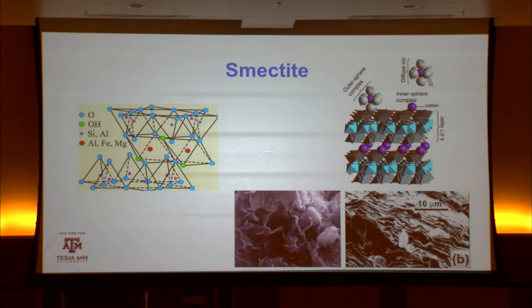So if you look over here to the right-hand side and you see the silica, oxygen, and silica layers, and then you see another basic stack of those layers, or another particle of clay, you can see that the clay is bonded, or these basic layers are bound together by these blue or purple circles, which are cations, positively charged atoms. And the reason for that is that nature does some substituting within the clay layers, so the clay surface is strongly negatively charged. So it attracts positively charged particles to its surface, like sodium or calcium or magnesium or potassium. And those positively charged particles try to neutralize that negative charge.